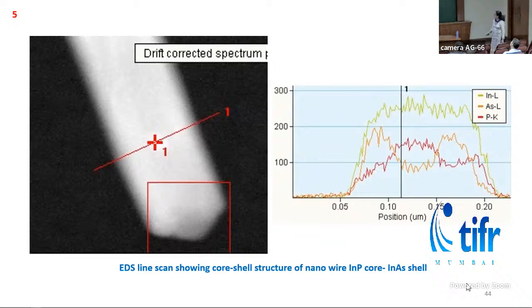This will answer your question a little bit. So this is a core-shell indium phosphide, indium arsenide nanowire, where indium arsenide is the shell and indium phosphide is the core. So this is the EDS line scan taken across this nanowire, and here we can see that arsenic is peaking at the edges because of the thickness. That means the shell is made up of indium arsenide and the core is made up of indium phosphide.